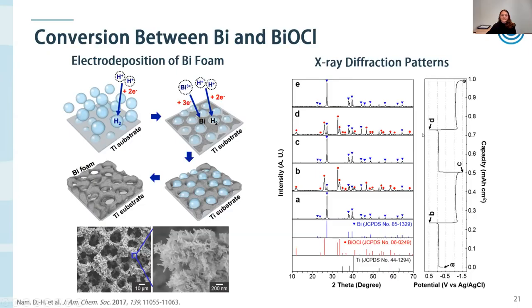And so I'm showing here these X-ray diffraction patterns, which I'll go through pretty quickly, that just indicate that when we make our electrode, it matches with bismuth metal, this blue graph here. And then when we do the oxidation reaction in a sodium chloride solution, we do form bismuth oxychloride, which corresponds to these red dots. And then when we do reduction, we go back to bismuth again. So really indicating that we are able to remove chloride using these bismuth electrodes.